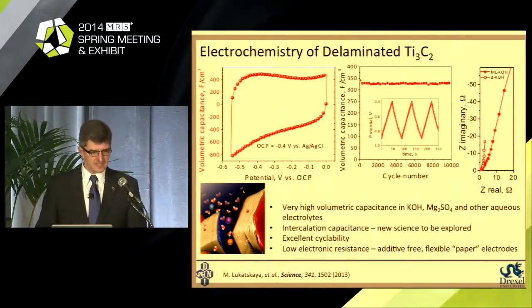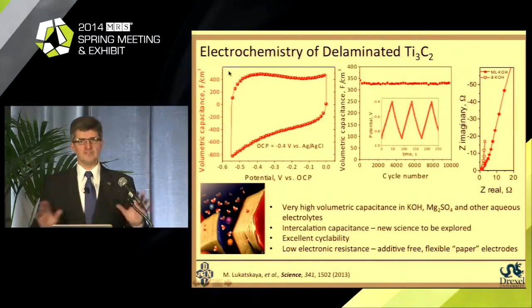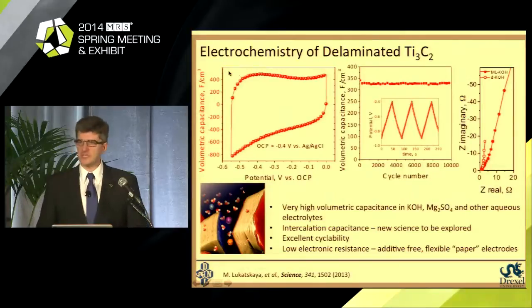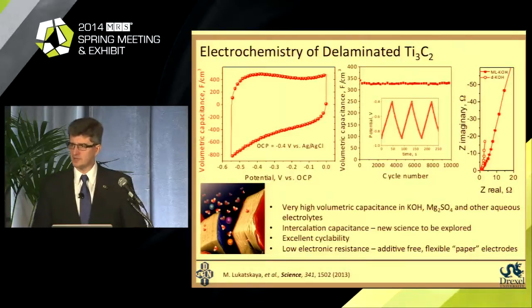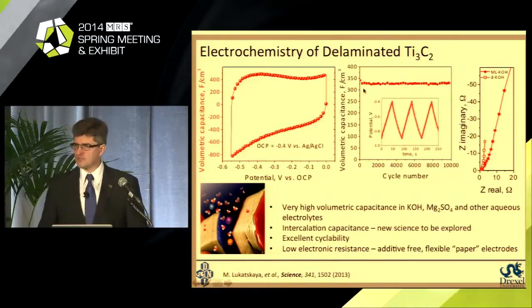We have excellent cyclability, and we have also good electrical conductivity. Moreover, I mentioned to you before, when I was talking about porous carbon film, that achieving 180 farad per cubic centimeter capacitance was pretty remarkable, because this is 3 times what commercial devices show. You can see numbers now exceeding those numbers by about a factor of 2.